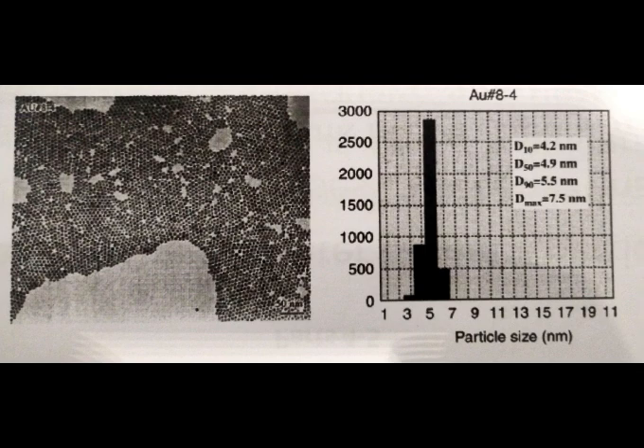Definitely. And the presentation highlights specifically monodispersed gold nanoparticles, and it mentions a diameter of less than 10 nanometers. So why gold? And what's the significance of them being so small and monodispersed? Well, gold is often chosen because it's an excellent electrical conductor, and it's also very resistant to oxidation. So it doesn't react with air and lose its conductive properties. Now, monodispersed basically means that the nanoparticles are all very uniform in size. So it's like having a batch of perfectly identical tiny little spheres.